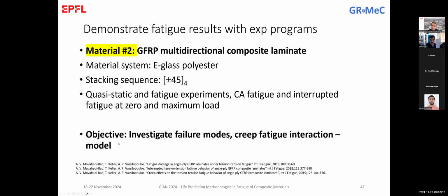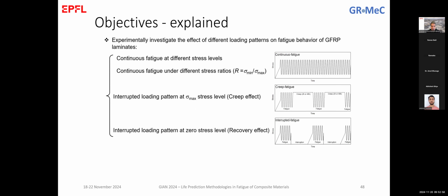It was because we had a specific objective, and in this case, the objective was to investigate the failure modes, of course, of the plus minus 45 degrees laminates that are, by the way, very common in engineering applications, and to investigate the creep fatigue interaction. Here I could add creep fatigue relaxation effects, and all this was in the concept of developing, in the end, modeling procedures to simulate this behavior, and if possible also to predict behavior based on these experimental results. I'll jump directly to the description of the experimental program.